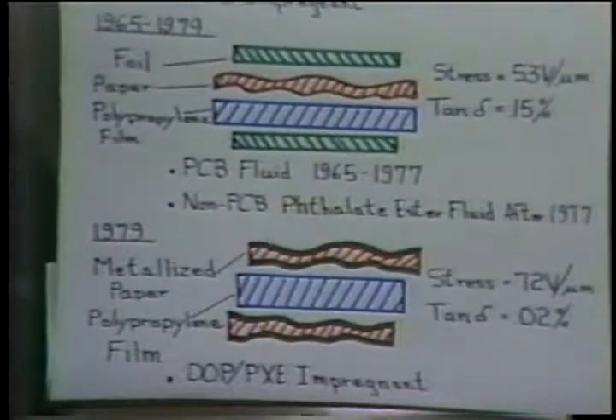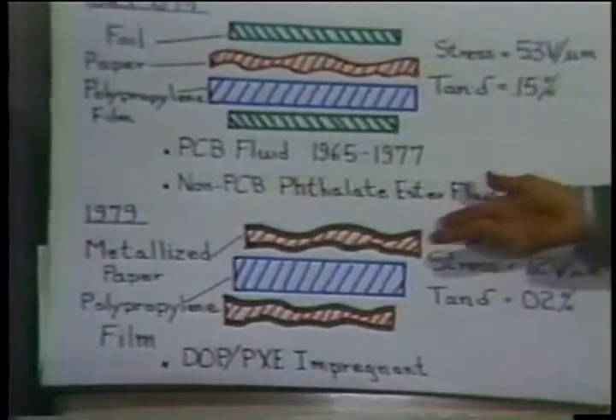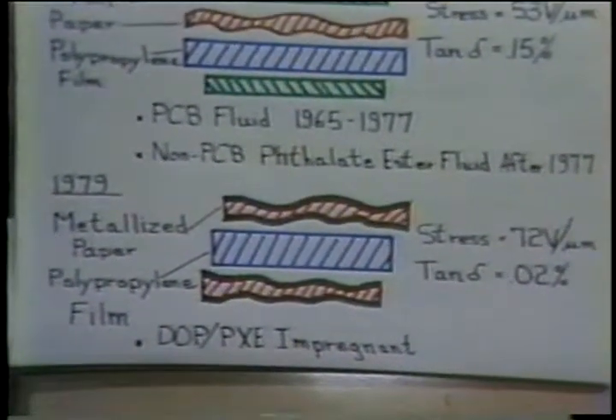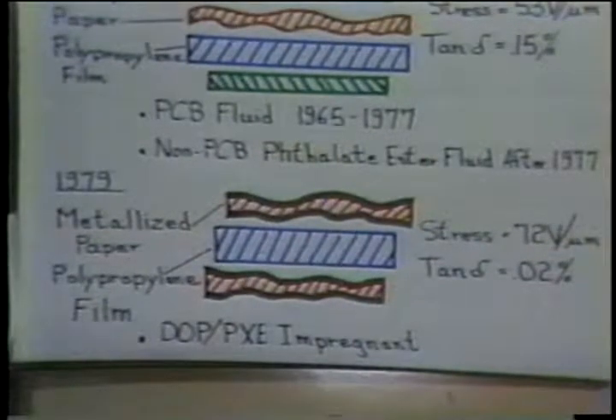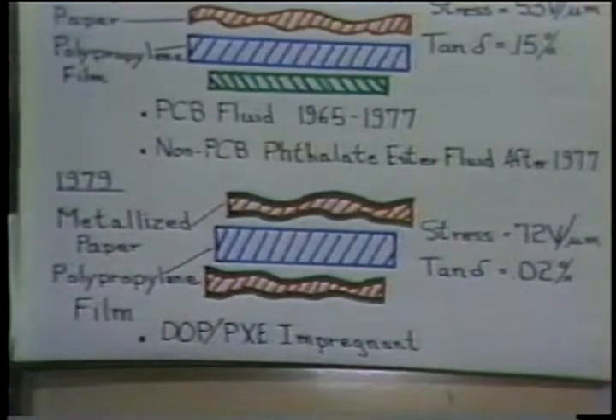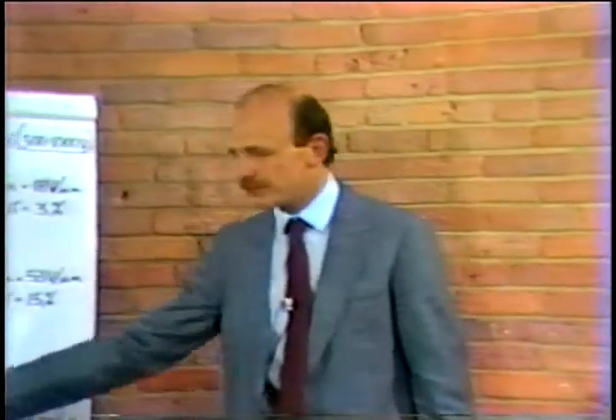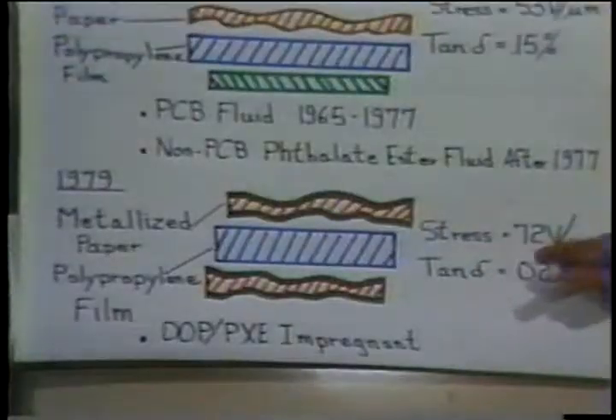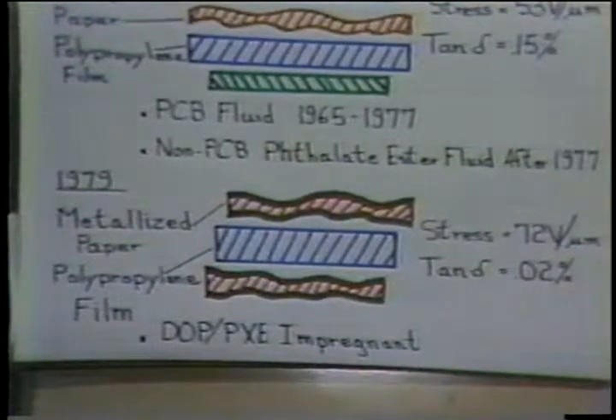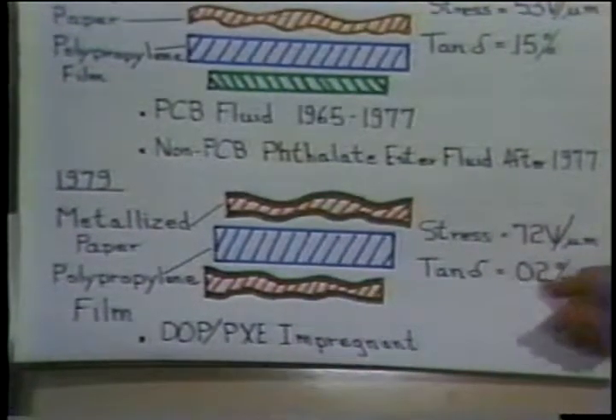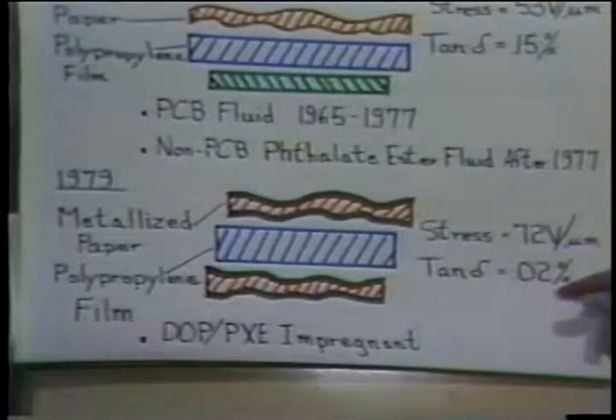In 1979, metallized paper and polypropylene film construction was introduced. Metallized paper allowed us to use a metallized construction and obtain the good clearability found with a metallized electrode. In addition, the rough surface on the paper allowed the full impregnation of this type of design. The stresses were increased up to 72 volts per micron. Again, because polypropylene was the main dielectric, the dissipation factor was 0.02%.